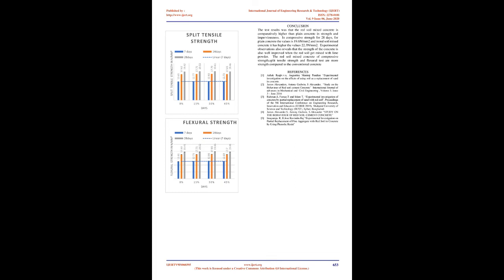Curing. Concrete derives its strength by the hydration of cement particles. The hydration of cement is not a momentary action but a process continuing for a long time. Curing can also be described as keeping the concrete moist and warm enough so that the hydration of cement can continue. More elaborately, it can be described as the process of maintaining a satisfactory moisture content and a favorable temperature in concrete during the period immediately following placement, so that the hydration of cement may continue until the desired properties are developed to a sufficient degree to meet the requirement of service.